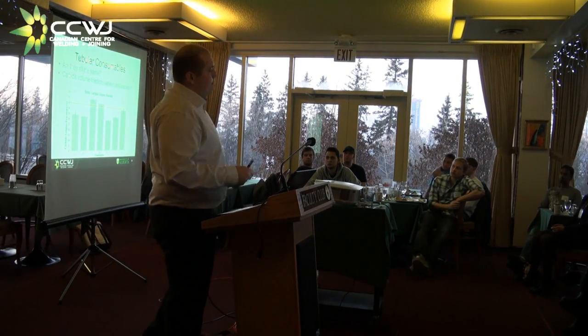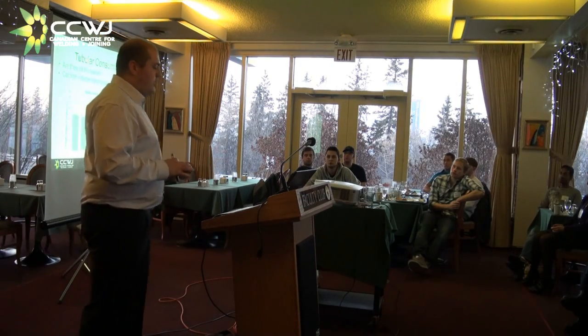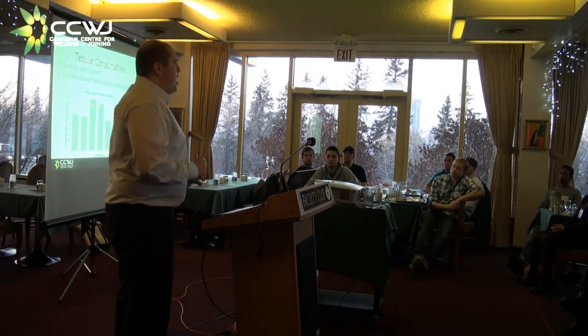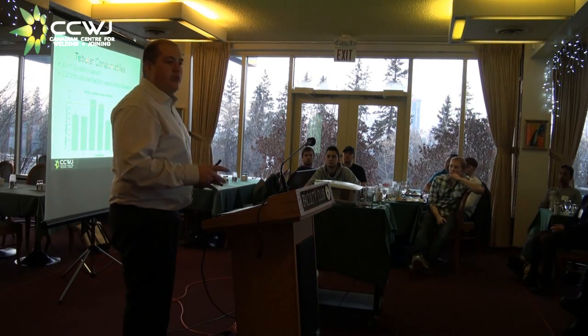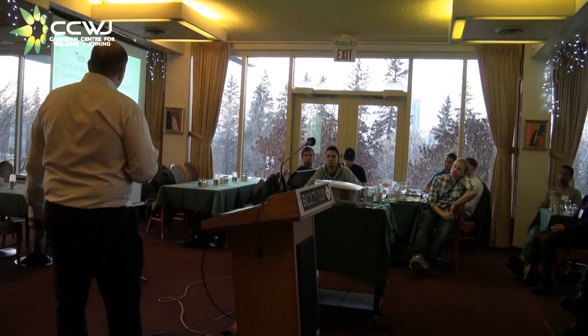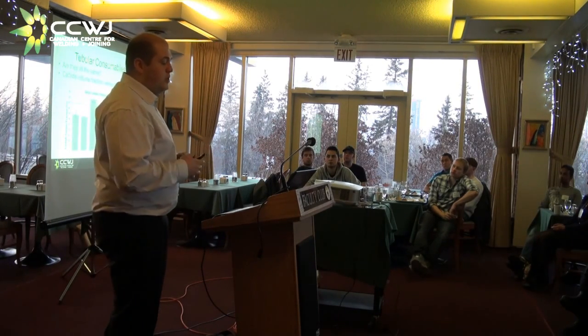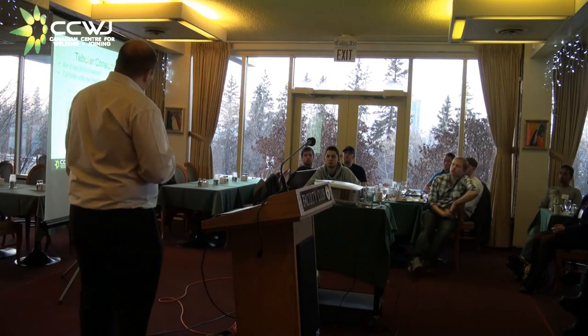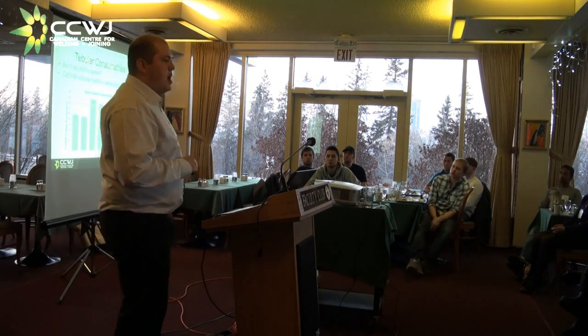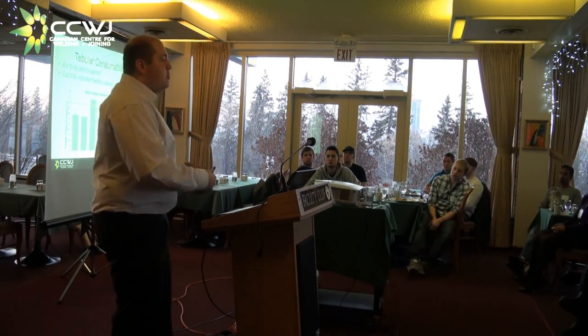So are they all the same? Definitely not. We've pried apart all these wires, measured them a couple of different ways, and all arrived at the same conclusion, that it really depends on the manufacturer and what the volume fraction in the wires is. I mentioned before that end users typically need 45 or 50 volume percent of tungsten carbide to have good wear performance. Well, if we look at this graph, there are only two, maybe three manufacturers of wires that meet this requirement, even before we weld it, even before we lose carbides during the welding operation. And this is a big deal.